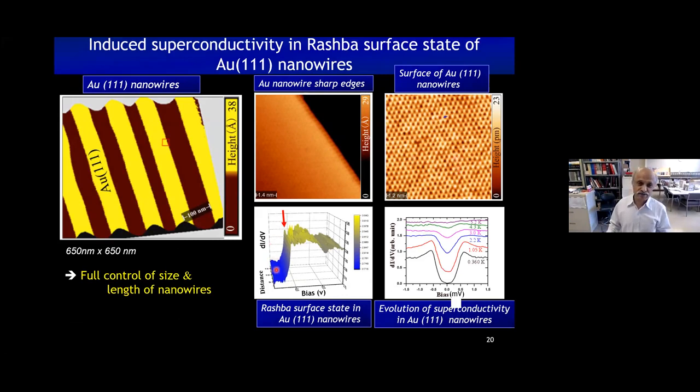What is also important is that after patterning all those things, the surface state is still maintained, as you can see. It's on the order of 0.45, 0.5 electron volt. Now, at the same time, when it's cooled down, as you can see here on the right side, it actually also shows superconductivity. That means the gold surface is also showing superconducting behavior. So this is by the STM. We have indeed kept the surface clean enough to have both the surface state and superconductivity still present in the system.